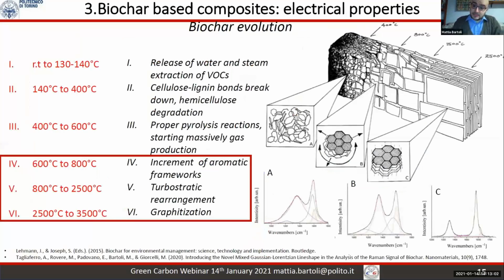But mechanical properties are not the only target when you produce a composite based on carbon materials. The other relevant property is the electrical conductivity of composites. And in this case, the story is a little bit tricky for biochar, because the electrical conductivity of biochar is strongly related to the temperature used to produce it. A good conductivity could be achieved for temperatures up to 800 degrees. And these kinds of temperatures require an investment in energy and cost. And we are looking around to see if this investment in terms of energy and cost could be counterbalanced by the properties. And the properties of biochar at higher temperature are very interesting.